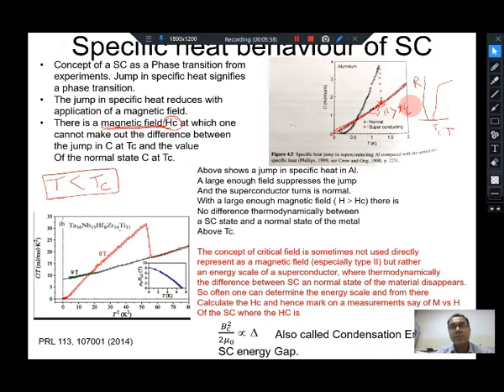Okay, so this is an example that if you don't apply the magnetic field, you see this nice jump, and this is characteristic of superconductors, that the entry into the superconducting state is via a jump in specific heat. This is another example. If you see this view graph below, just below the superconducting transition you see a large jump in specific heat, but if you apply a large enough magnetic field, you can suppress this jump in specific heat completely, and what you see is the behavior of specific heat of the normal state of the material.